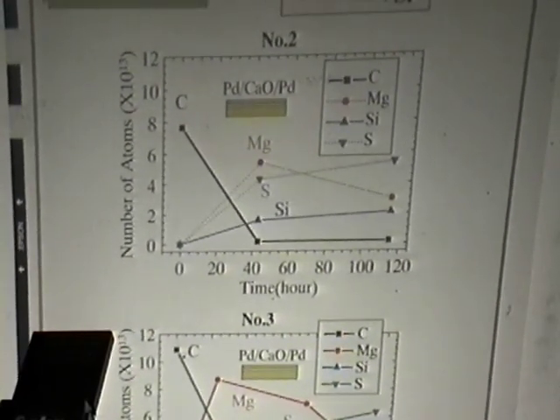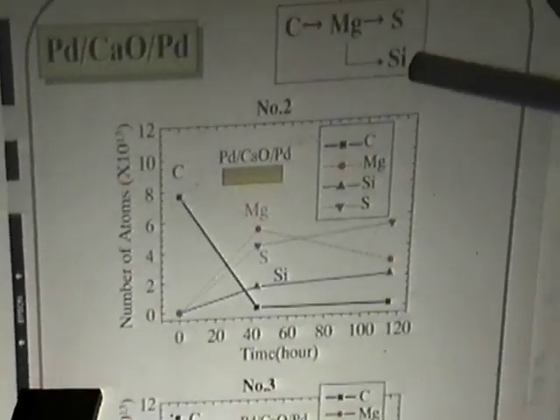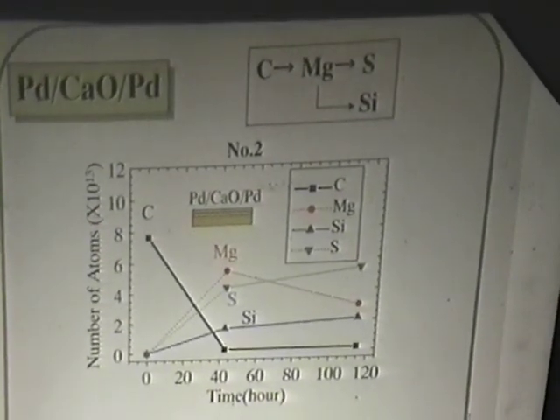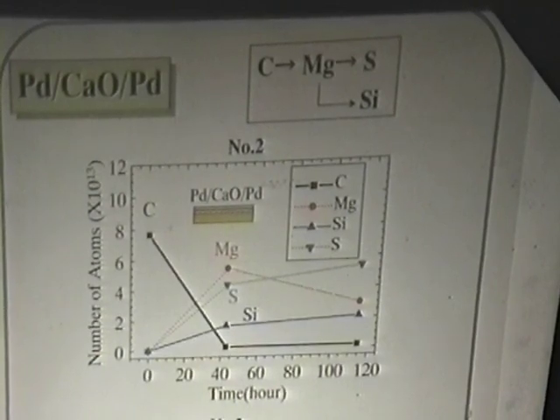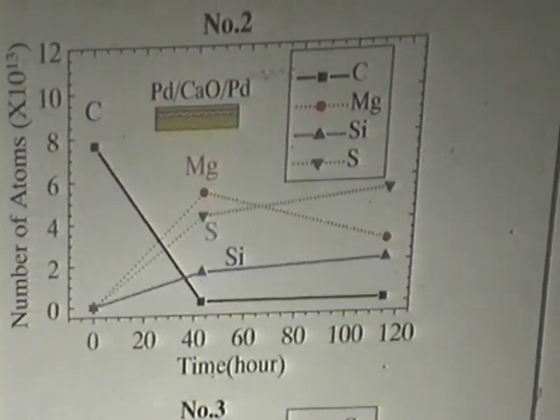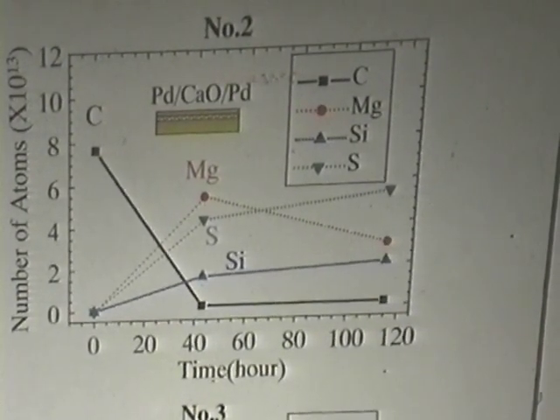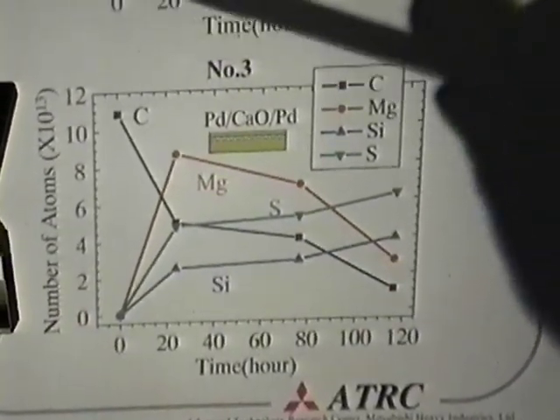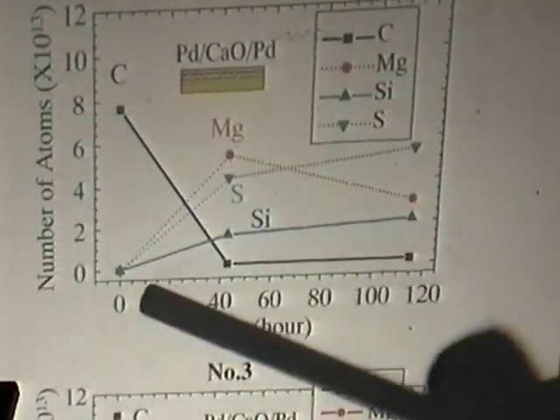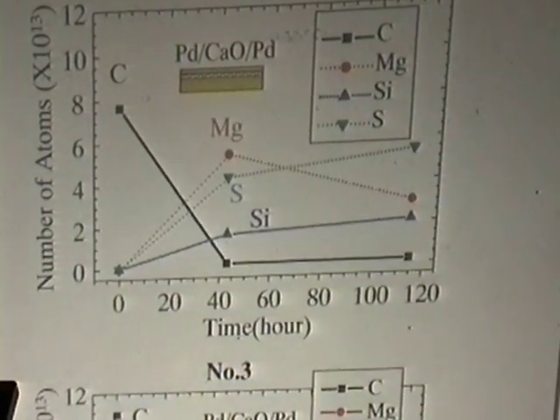These figures show the time dependence of impurity carbon, magnesium, sulfur, and silicon on the multilayer palladium. The multilayer palladium is composed of palladium, calcium oxide, and palladium. And we performed this type of experiment two times. Okay. At T equals 0, no element except carbon can be found, of course.